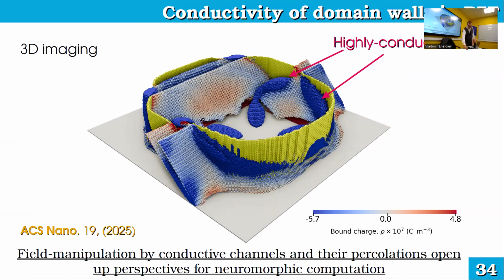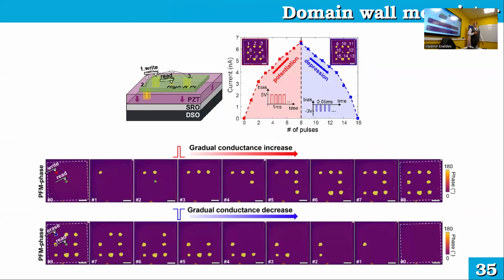And basically what experimenters show here, so if you read conductivity somewhere in the center of material, and upon creating some repolarized spots, you get higher and higher conductivity. Upon reverse repolarization, you have lower and lower conductivity. And basically, this is pretty interesting from an application point of view, because such a ferroelectric can be used instead of a memristor in these cross paths with different reprogrammable conductivity levels.